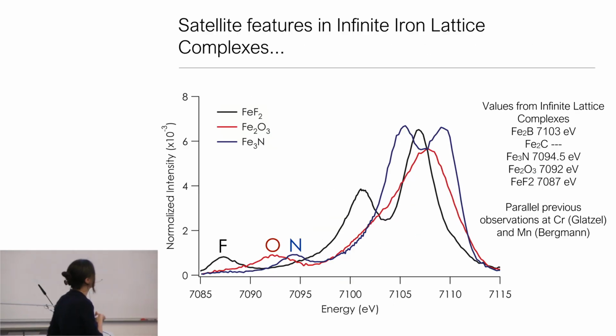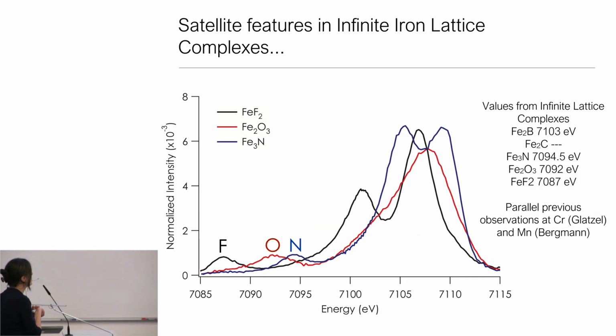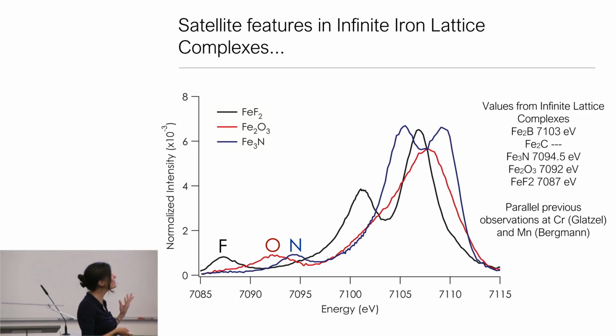And that's particularly true for these incredibly weak 2s features. You can see that the valence P levels that are actually involved in bonding undergo stronger modulations. But as we already discussed, because of the energetic separation of the 2s orbitals, they're less likely to be involved in bonding. And these energies rather report on the differences in ionization energies going from fluorine to oxygen to nitrogen. And you can see, this is nearly 10 electron volts that we span in 2s ionization energies. And so it makes it quite a sensitive probe, and it's a universal probe.